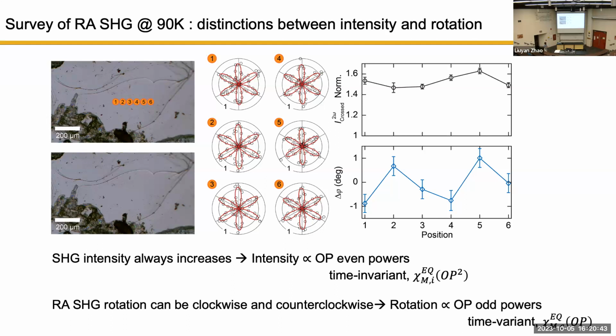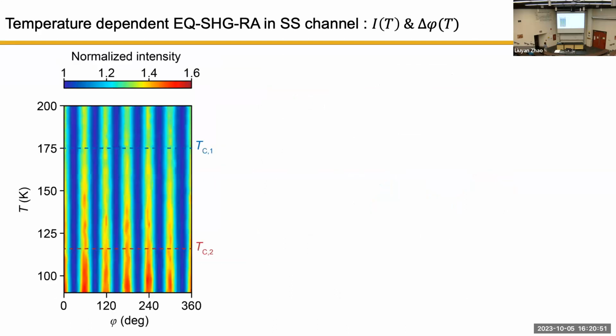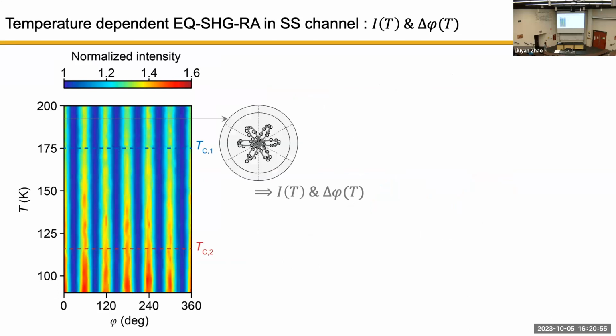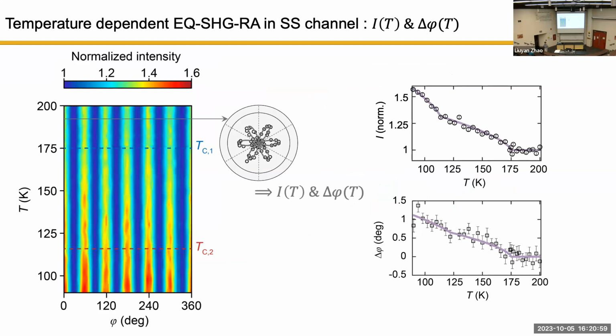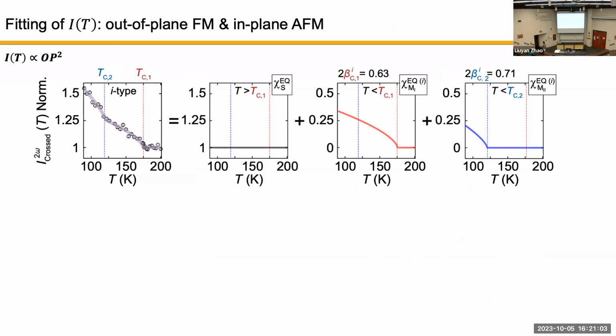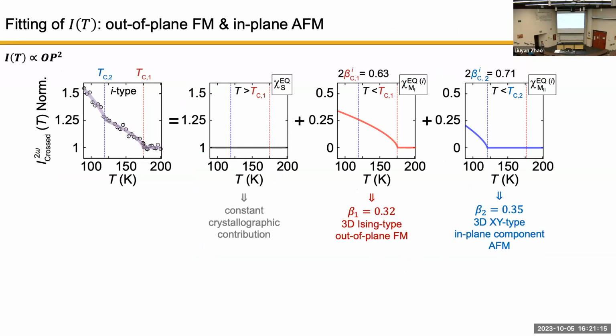So our analysis is to attribute one as proportional to the order squared, the other as proportional to the order itself. Then we can do this kind of temperature dependent flower pattern to separate out the temperature dependence of the intensity and orientation. The main result is that for the intensity, we have three contributions: one from the bare structure, one from the first phase transition, one from the second phase transition. What's impressive is that the first and second phase transitions have different exponents, and they nicely match some theoretical models. The first one matched a 3D Ising type of exponent, while the second one matched a 3D XY type of exponent. For the first one, it makes sense because I'm dealing with out-of-plane ferromagnets. It's an Ising type thing.